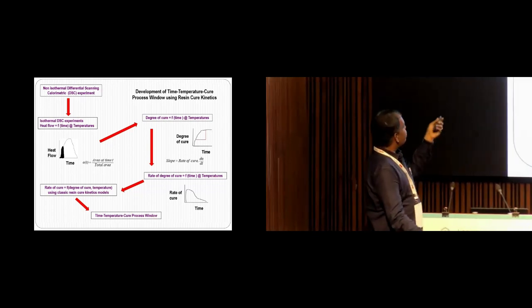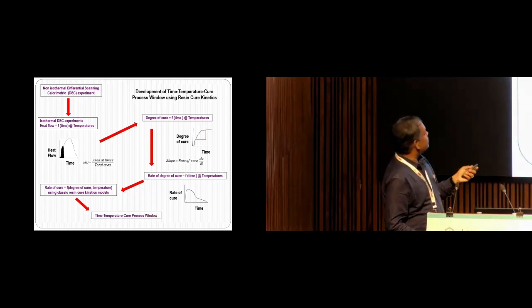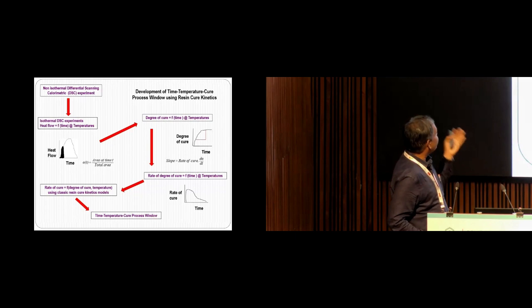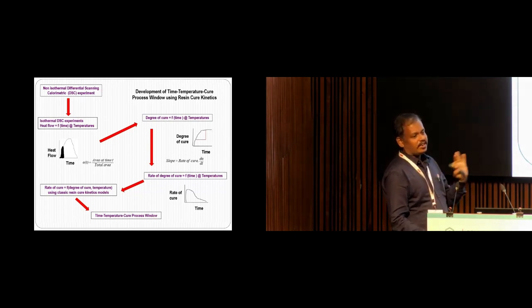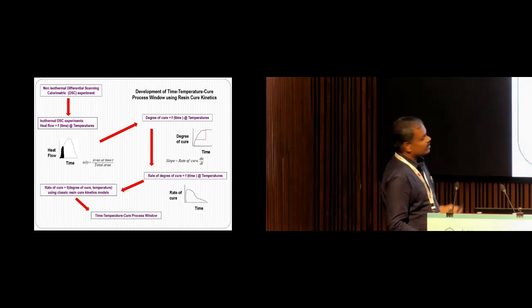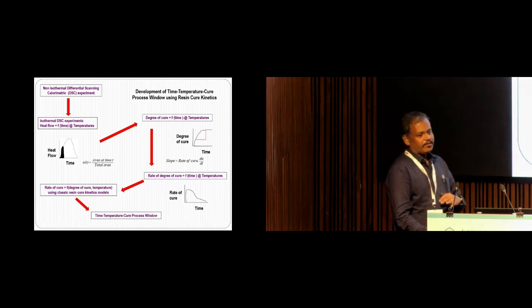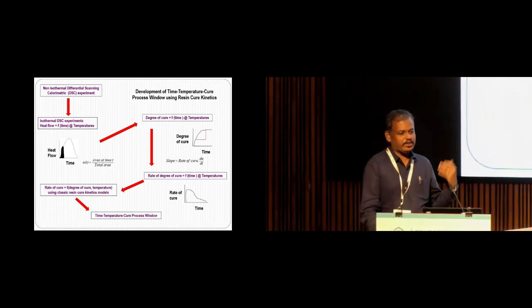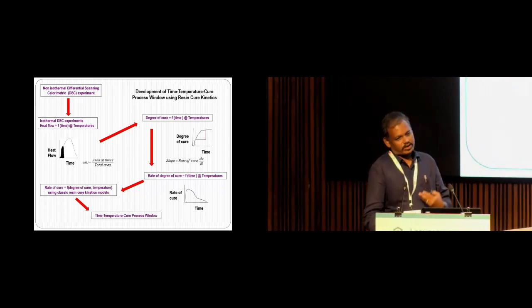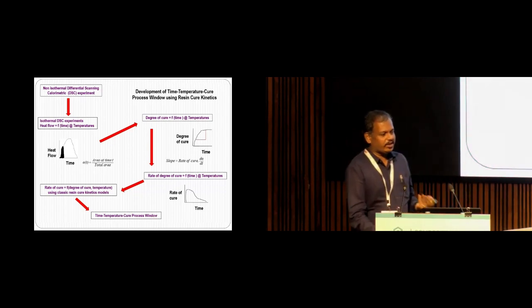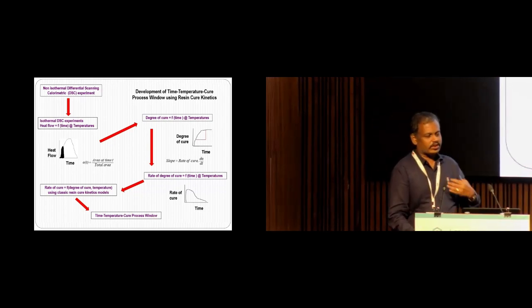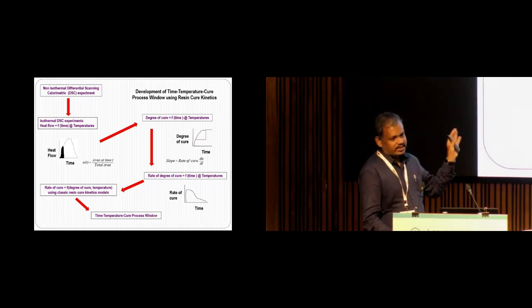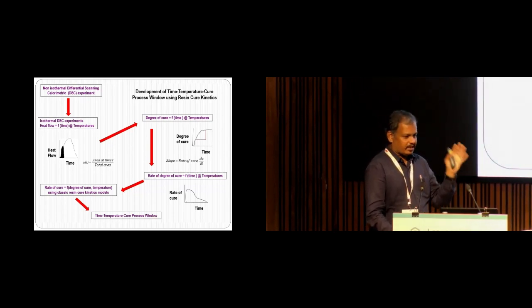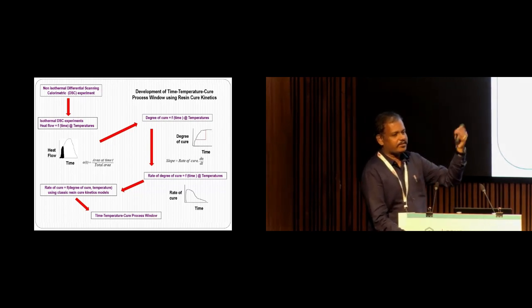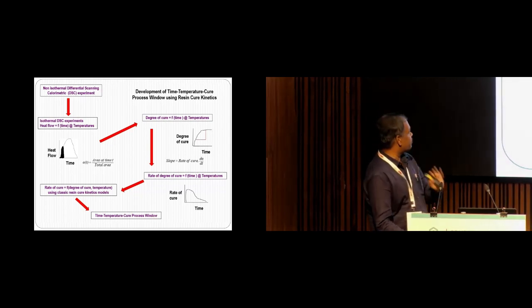Once I perform the isothermal DSC experiments, you will get a plot of heat flow as a function of time at different isothermal temperatures. I can get the degree of cure from this plot by taking the partial area divided by the total area. The total area gives you the total heat of evolution, and the partial area gives you the heat at the particular time. So partial area divided by total area will give you the degree of cure.